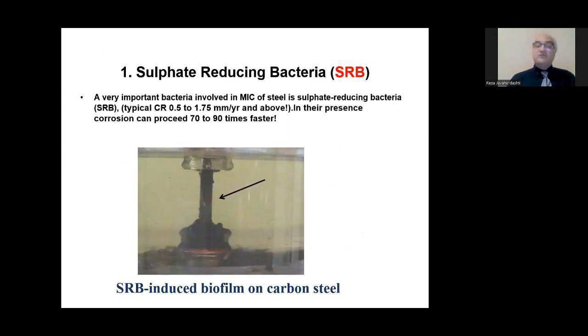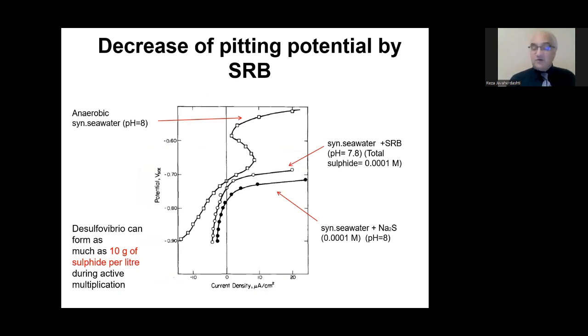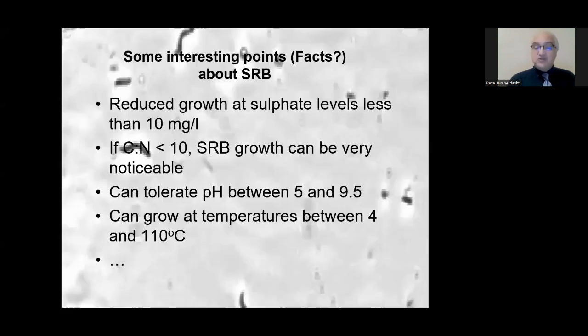All right, sulfate-reducing bacteria, SRB. What they do, they reduce sulfate, SO4, to sulfide, S-2. They can induce corrosion rates around 2 millimeters per year or above, and in their presence, corrosion can proceed 70 to 90 times faster. We have some electrochemical evidence for that: in the presence of SRB, pitting potential could be reduced to low values, meaning that the material will fail in a much shorter time.